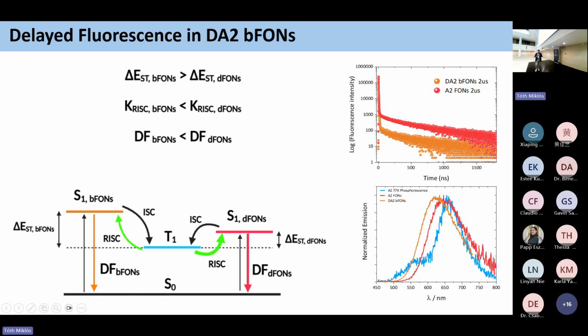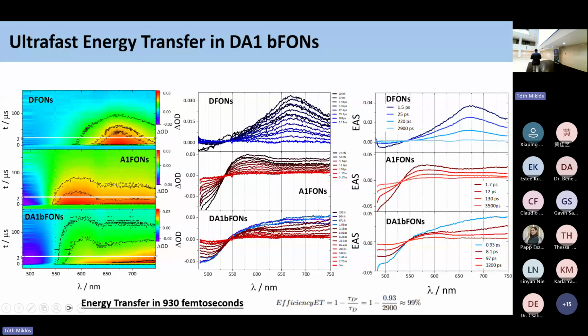So from TCSPC, we say that the energy transfer must be very fast, and we went deeper into this by performing femtosecond transient absorption spectroscopy on the samples. Here I have reported the time resolved 3D data matrix, the time resolved spectra, and the evolution associated spectra derived from the global fit on the matrix for the single component nanoparticle of the donor and the acceptor, as well as for the DA1 binary nanoparticle. We see that the signal for the donor is dominated by a broad excited state absorption centered at 670 nanometers, while for the acceptor we have a very broad excited state absorption between 550 and 750 nanometers with a ground state bleaching at 500 nanometers.